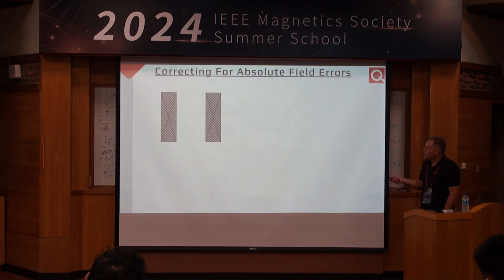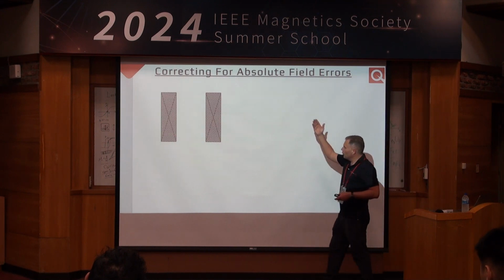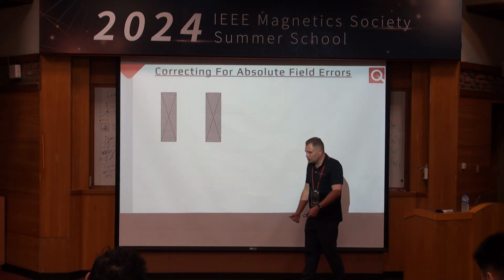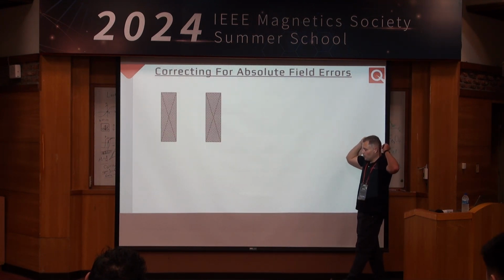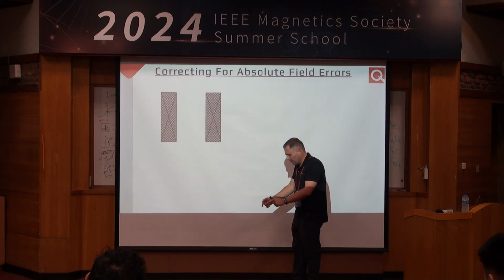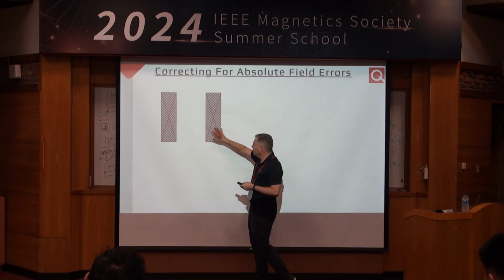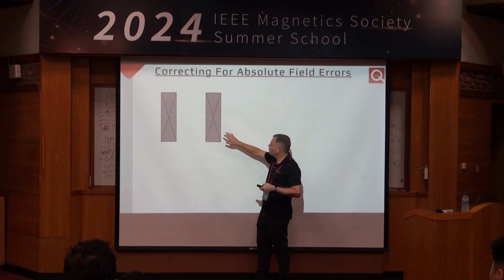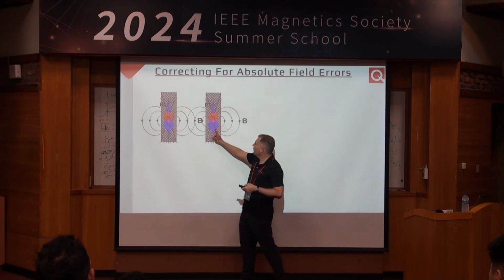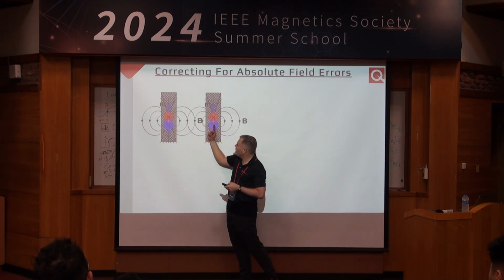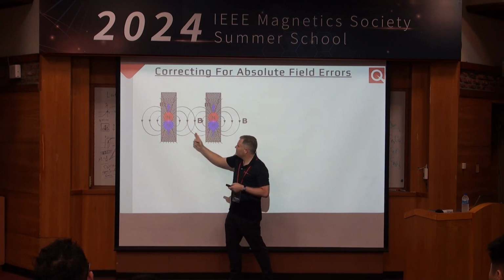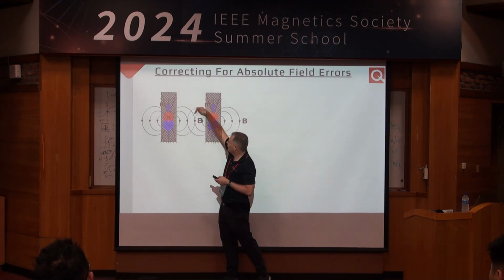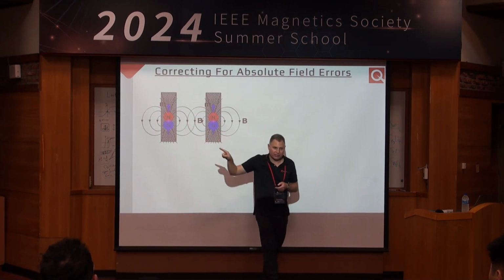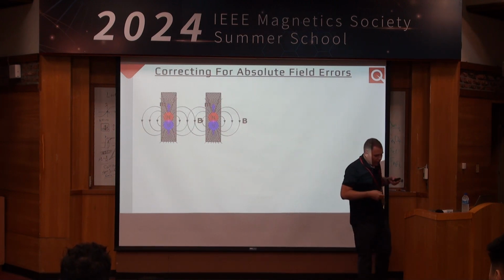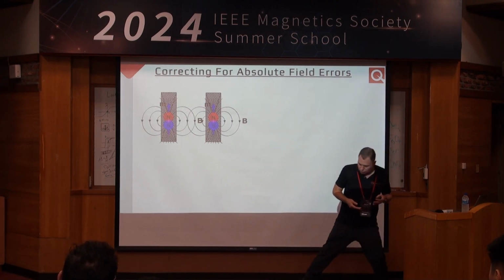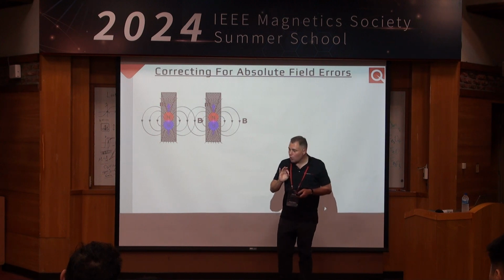But again, let's say this is our superconducting solenoid in cross-section, and we've charged it all the way up to 16 Tesla. We then go to 0 Tesla. Well, we're going to have some trapped flux inside this magnet, which would correspond to having a magnetic moment in the body of the coil pointing upwards. So that means the stray field from these moments is going to be pointing downward at the sample location. And that's a general thing. When you positively saturate your sample and you come straight to 0 field, you're going to have a small negative